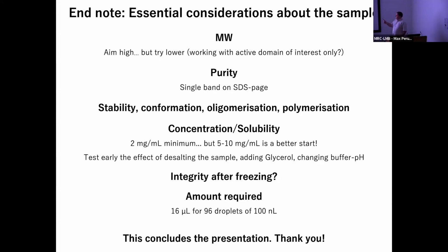A big one is also integrity after freezing. The first thing I will ask before someone does optimization: did you get your initial hits with a fresh sample, and now you're working with frozen sample because you keep some to do your optimization later? You may have surprises here. In general, freezing a sample doesn't help. Sometimes it doesn't make any difference, and that's great because you can work with frozen sample, you can do something 3 weeks later, but sometimes it makes a difference. So you do want to have a go with freshly produced sample anyway, and then see if you can work with frozen sample. Again, just a little reminder, if you go to the crystallization facility, you need 16 microliters at least to do 1 plate.